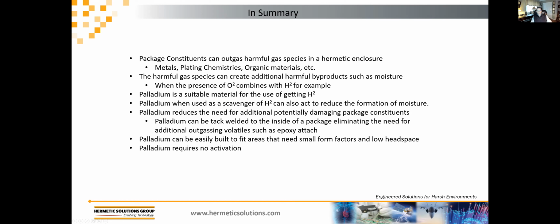We understand palladium is a suitable material for gettering hydrogen, and that it will reduce the formation of moisture. The neat thing about palladium is that, although not in all cases are you able to do this, palladium can be tack welded to the inside of a package, eliminating the use of epoxies or other materials to hold it in place. So you eliminate one level of materials that can outgas volatiles into the package.